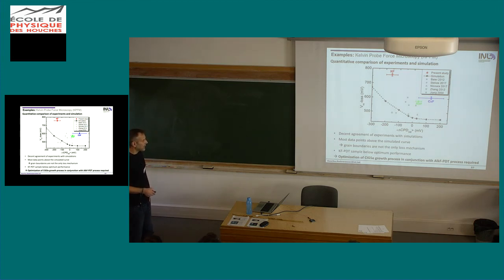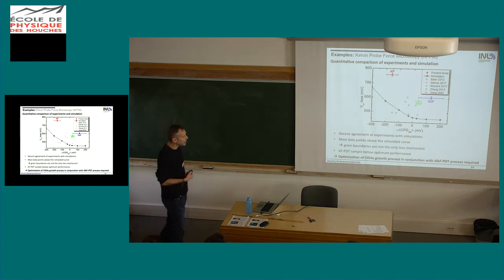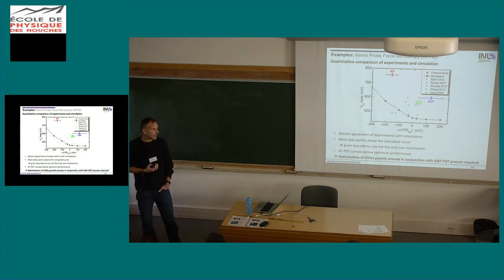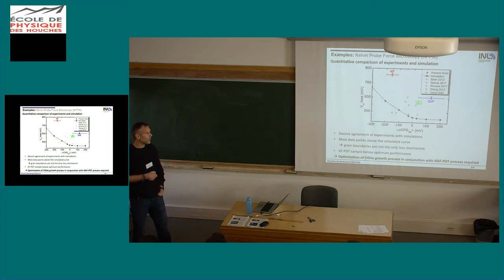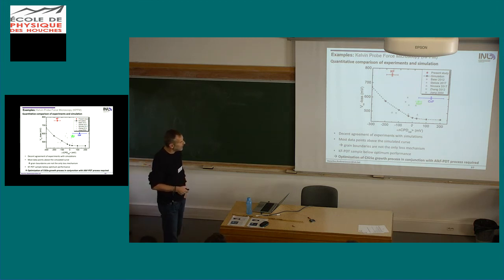One thing that I mentioned slightly is that the potassium fluoride treated sample is below what it can actually perform, so that one should have a much lower open circuit voltage loss. And this tells us that you need a fairly good fine-tuning of the conditions of your alkali fluoride treatment in combination with a CIGS surface. So it's not just simply evaporating alkali fluoride on top, but you have to optimize the process for your absorber. And this one was not completely optimized. But it tells us that if we have large band bending at the grain boundaries in terms of an electron barrier, then we have a loss in our device.